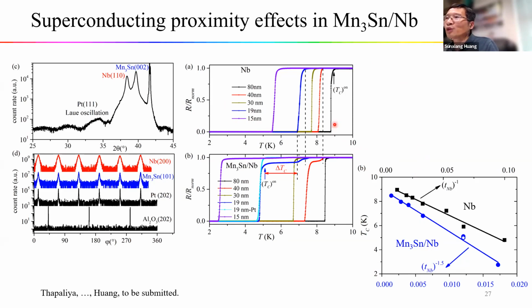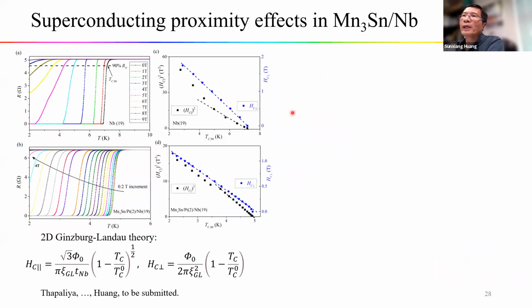To study the possible triplet pairing in these systems, we did RT measurements at different in-plane and out-of-plane fields. From these RT curves at different fields, we can obtain the upper critical field and the corresponding transition temperature. So we plot the out-of-plane critical field as a function of the temperature. It shows that for the out-of-plane field, the critical field scales linearly with the critical temperature.